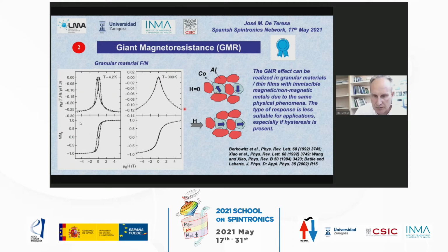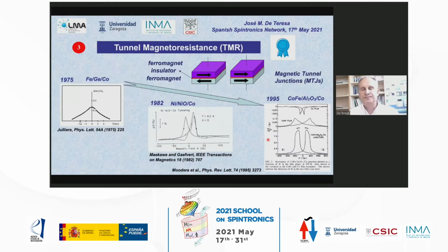In fact, this is what one can observe as one magnetizes this granular material: one observes a decrease of the resistivity. Okay, this type of response is less suitable for applications, especially if there is some hysteresis. So in many cases at low temperatures, you observe hysteresis. Good. So now we change gears and we proceed to the next spin-dependent transport phenomenon to discuss in detail, the tunnel magnetoresistance.